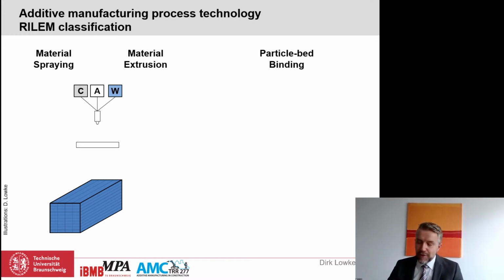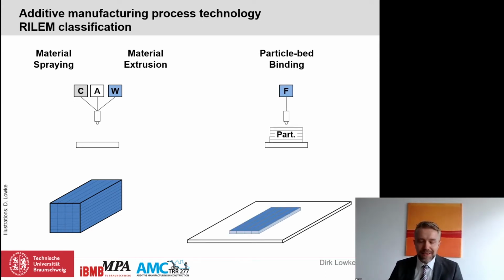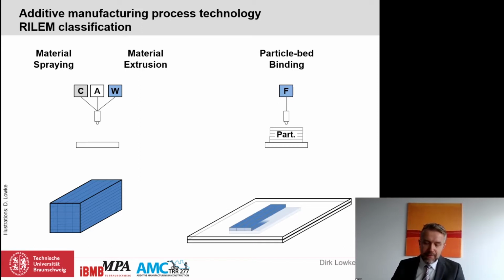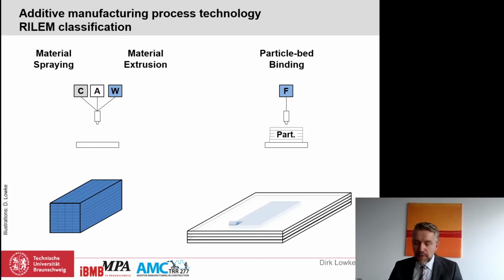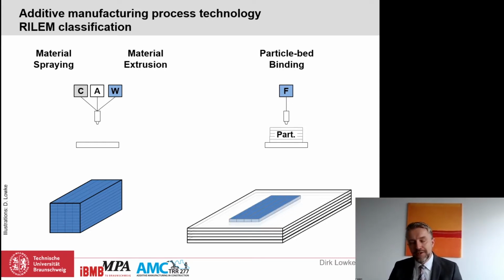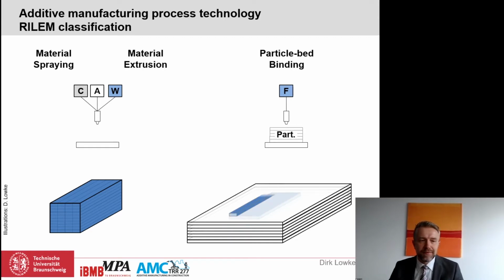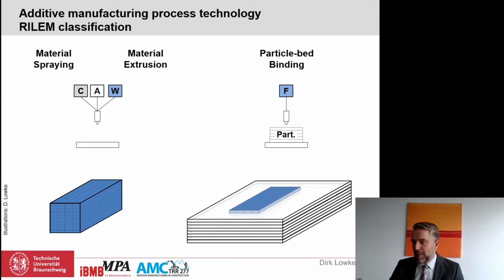The alternative I want to talk about today is the particle bed 3D printing or particle bed binding, where we selectively bind the particles in the particle bed. Here in the first step, a layer of dry particles is spread, and subsequently a liquid is selectively applied onto the particle bed in order to locally bind the particles. After finishing the printing procedure, we have to remove the non-bound particles from the particle bed, and finally we have built up our concrete element.